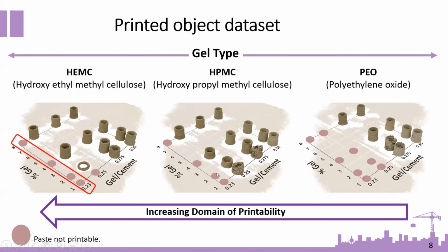Our experimental design included a 4x4x3 factorial design. We varied the gel to cement ratio, and also varied the gel percent, and we printed a benchmark hollow cylinder object based on the 3 hydrogel forming polymers. As you can see here with the naked eye, as we move from right to left, from polyethylene oxide to hydroxyethyl methyl cellulose, the domains of printability improved and the quality of the printability improves.